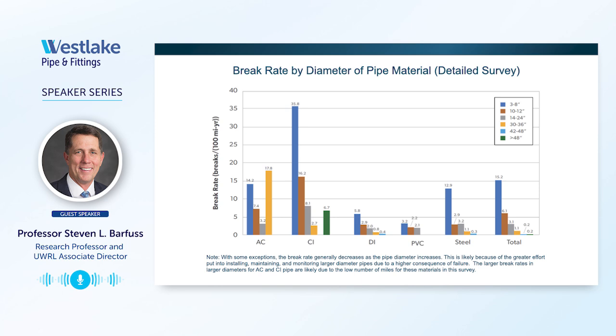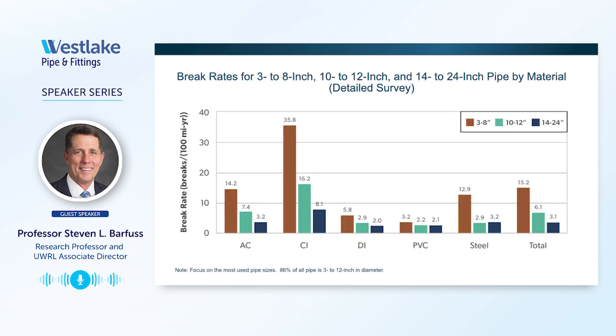This is break rate by diameter of pipe material from the detailed survey. And back to your question about detailed versus basic. Diameter, you'll notice one of the interesting things is there seems to be an increased trend in break rate as you get smaller diameter. And if we move to the next slide where we zoom in on these three smaller ones, these smaller size ranges of pipes, clearly there's a trend where the break rate increases as you get smaller and smaller sizes. Some of that may have to do with the amount of pipe that you're reporting, but there is a correlation.